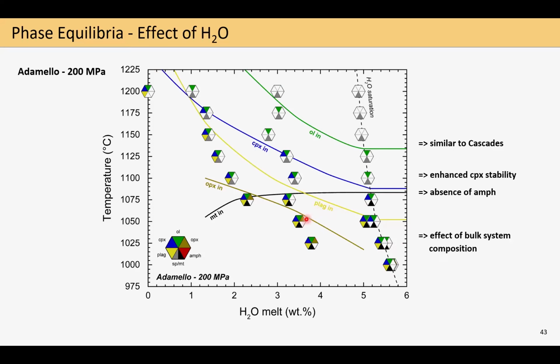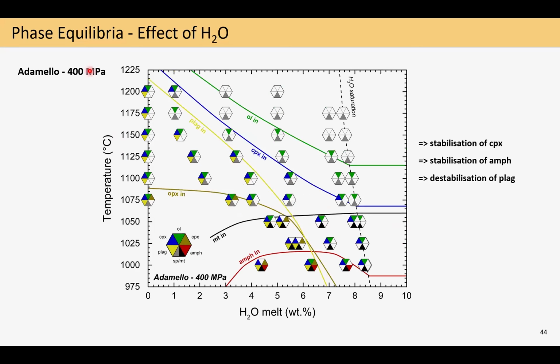And we can also have a look shortly at the 400 megapascal data for the Adamello, where we see a stabilization of clinopyroxene, an overall stabilization of amphibole, now it is there, before it was not, and a general destabilization of plagioclase with increasing pressure, resulting in that even the highest water series here are not saturating in plagioclase upon progressive crystallization. So here we see a distinct pressure effect on phase equilibria.